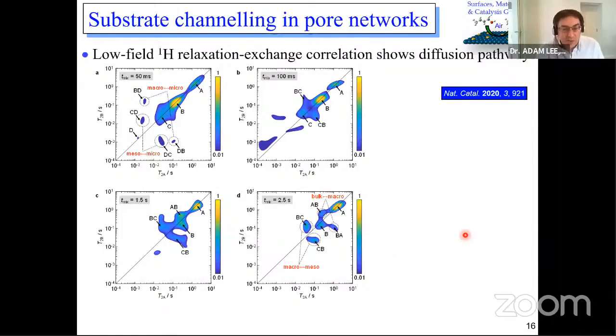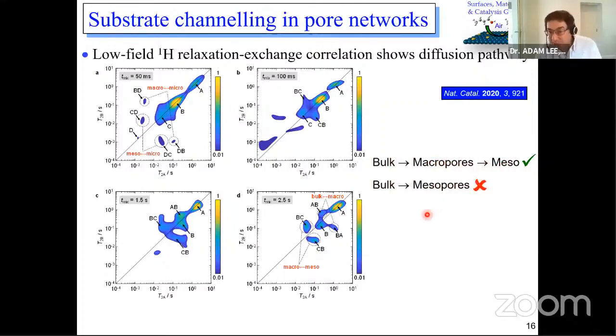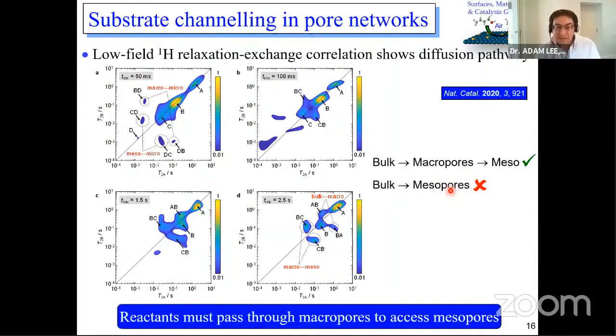Okay, so I've said a lot of words there. What does it mean? It means that our catalyst allows molecules to move from the bulk reaction mixture into the macropores, and from the macropores then into the mesopores. However, we cannot move molecules directly from the bulk reaction mixture into mesopores. Why is that important? It's important because it means that reactant molecules have to go through macropores where our first catalyst site is located before they can move to mesopores where the second catalyst is seated. In other words, we now control the reaction sequence.